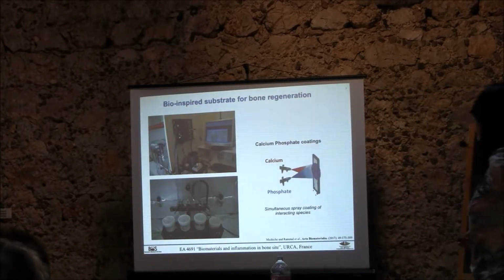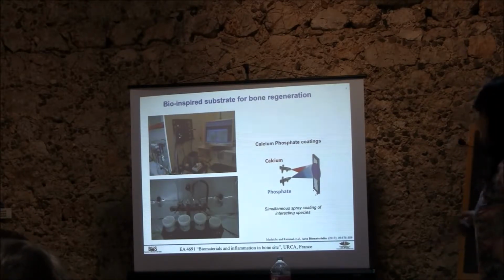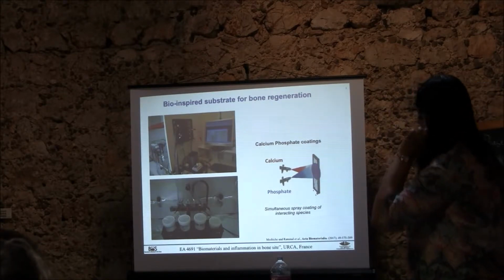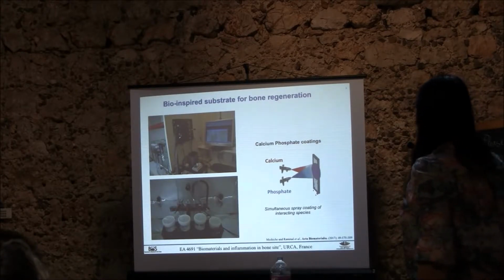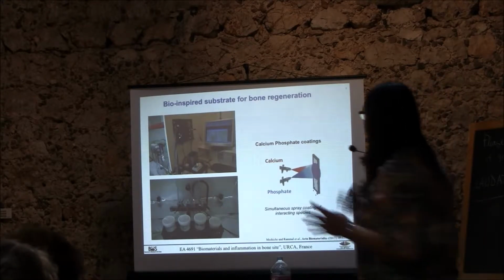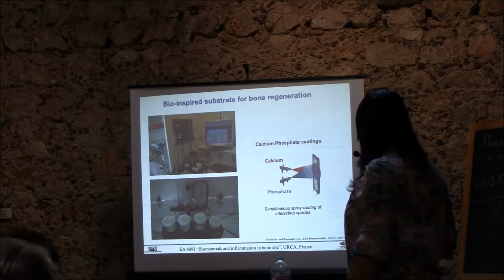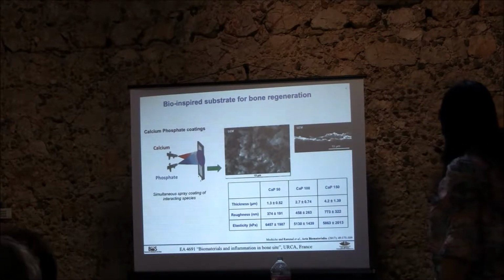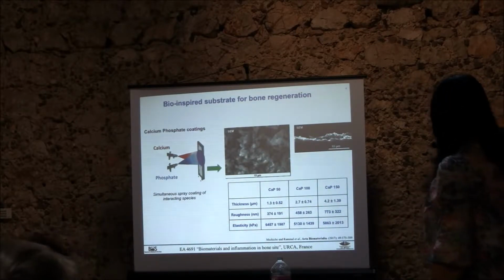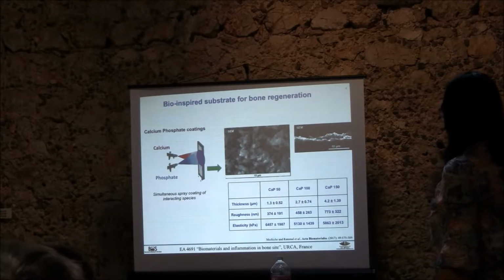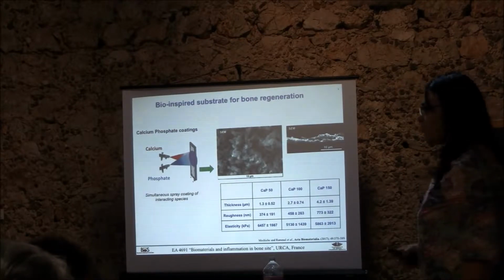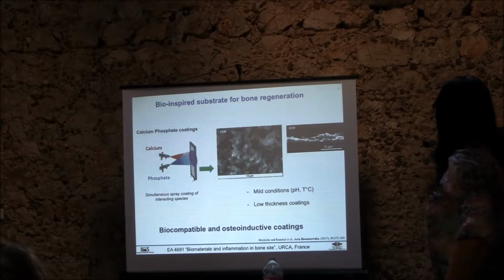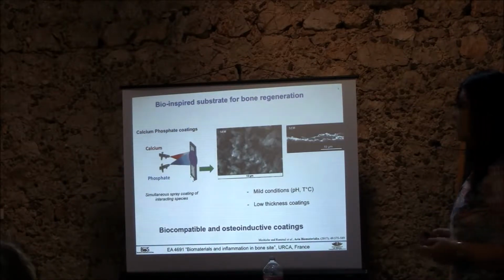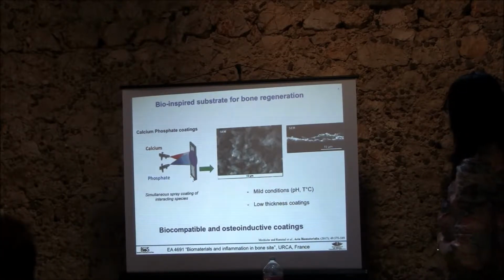In our laboratory, in collaboration with the team of Pierre Schaff in Strasbourg, we developed automated simultaneous spray coating. Under controlled pressure and environment, we sprayed simultaneously solutions saturated with calcium and phosphates. We obtained a coating with spherical calcium phosphate, and we could modulate thickness, roughness, and elasticity of the coating by increasing the number of spray cycles. Our setup was conducted under mild conditions in pH and temperature, and we tried to introduce some molecules.